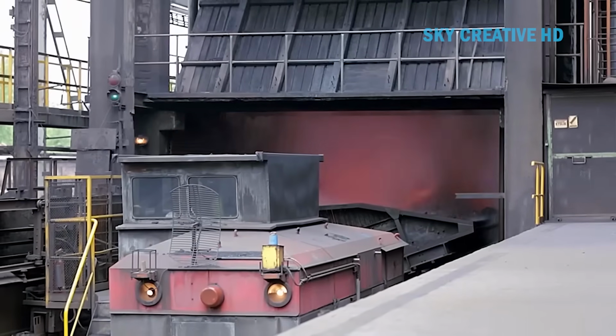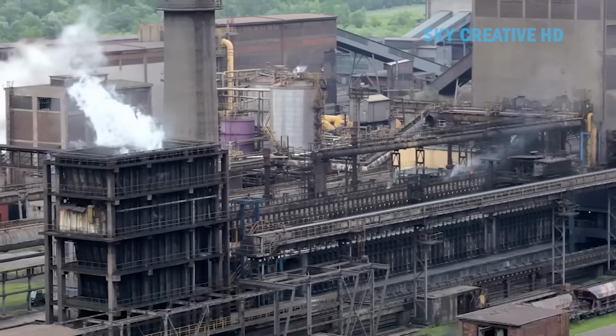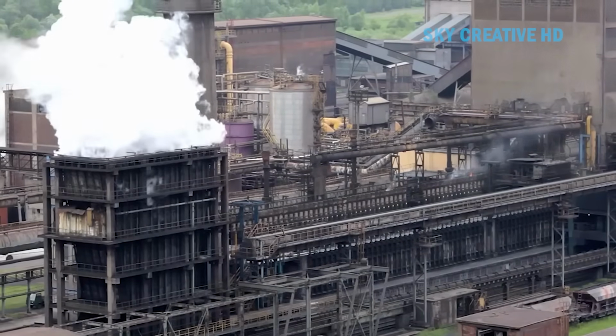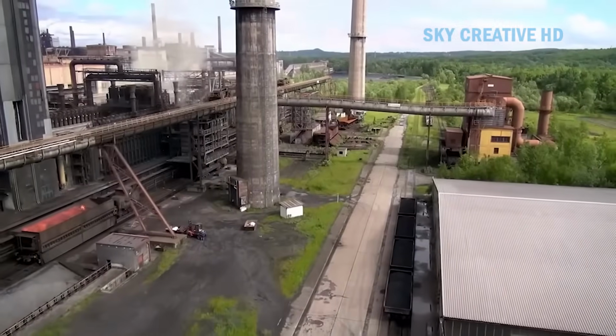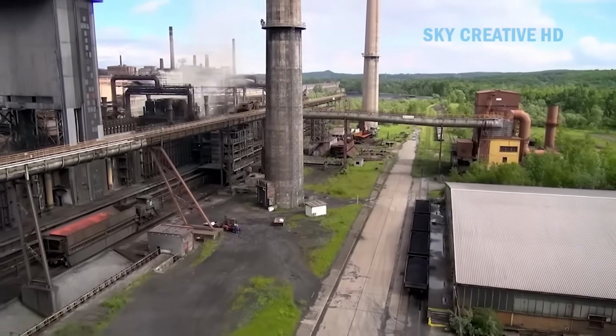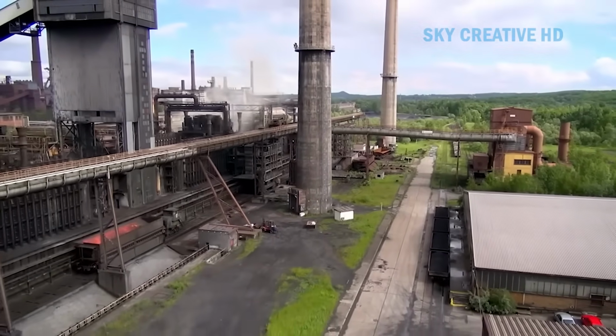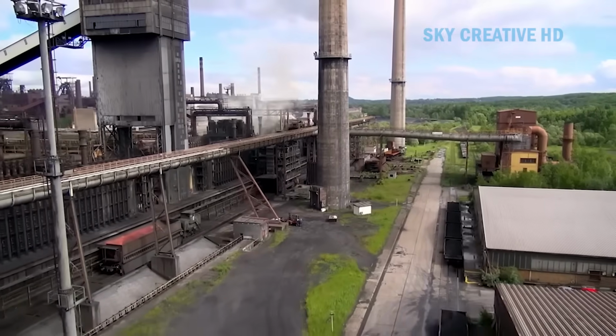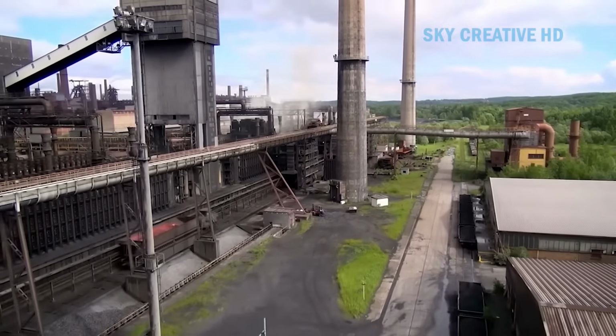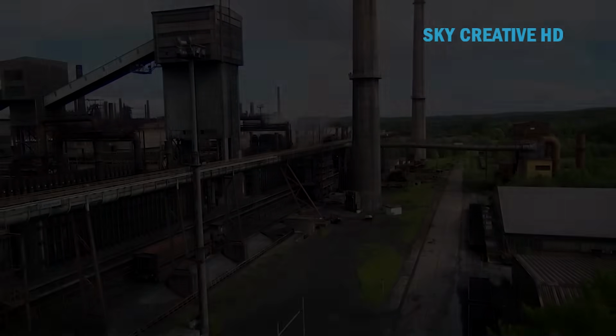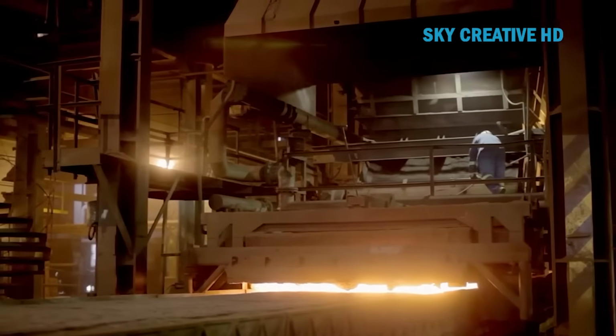The transformation happens in the basic oxygen furnace, where pure oxygen is blown onto the molten iron at supersonic speeds. This process removes excess carbon and other impurities, and the precision required is remarkable. Too much oxygen and the steel becomes brittle, too little and it remains too high in carbon content. The chemistry happening here is fascinating.